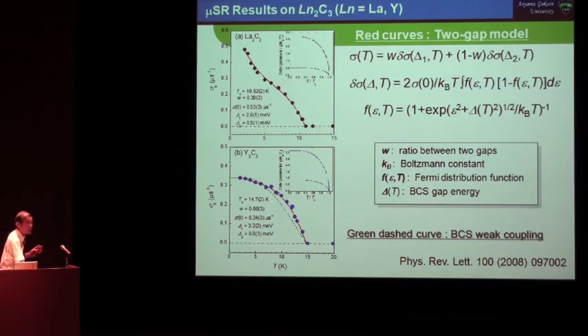This two-gap behavior is closely connected, but in La2C3 they are almost independent, so we can conclude that TC is finally one, but from the gap state it seems that almost two gaps exist.